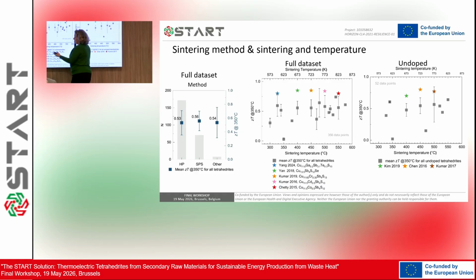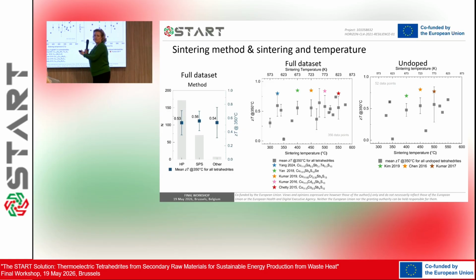And it's very surprising because from here to here, how can it be possible that when you sinter at 320 or you sinter at 550, you get the same result? Because this is what it tells you. It tells you that the sintering temperature is not a variable, it's not important. And that is, again, very strange, and it suggests, again, that there is something wrong with the processing.